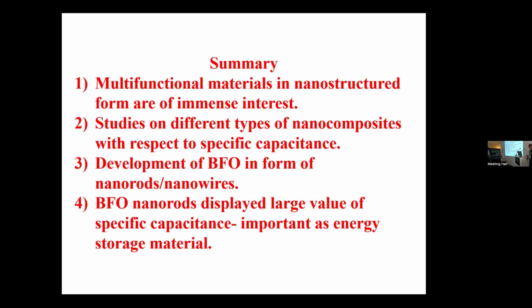So in summary, these multifunctional materials in nanostructured forms are of immense interest, and we carried out studies on different types of nanocomposites with respect to specific capacitance, and on the development of bismuth ferrite in the form of nanorods and nanowires. And the bismuth ferrite nanorods displayed a large value of specific capacitance, which may be important for pseudo-capacitive materials.